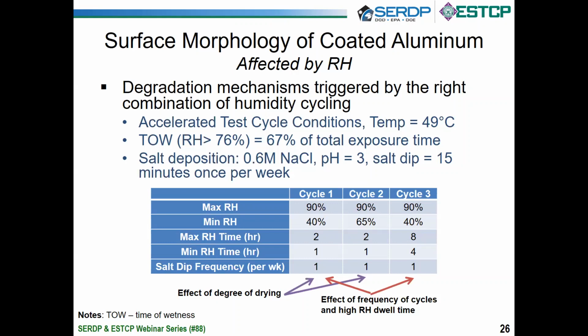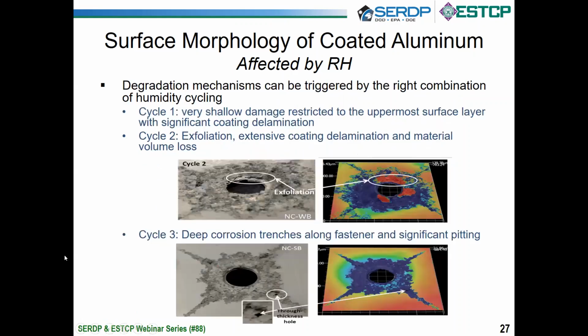And in the last, we fully dry it, but we completely change the time of wetness. So this is the absolute time of wet in any given cycle is increased by a factor of 4. And let me point out that all of these have the same total time of wetness through the test. The other thing that I'll note is we only put salt on this once a week. This is basically a modified ASTM G85, so acidified salt, and we put this through this cycle. That salt was only applied once a week by dipping the panels. You'll see in the next slide the kind of damage that we see. I don't have an image of the first one. I can tell you that there was delamination, but there was very little depth of the attack.